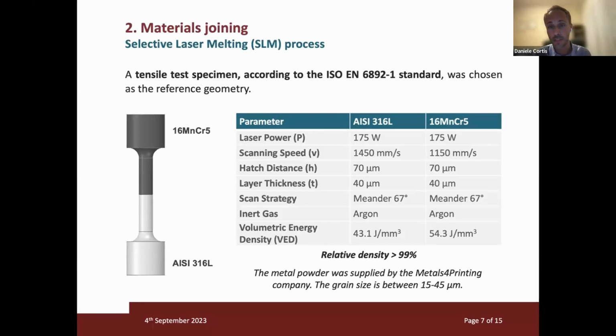Here you can see the process parameters. As you know, the main parameters for this kind of process are the laser power, the scanning speed, the layer thickness, and also the hatch distance, that is very important in our case because we have a very fine laser spot. And of course, you can summarize all these parameters with the volumetric energy density, that is an index for the evaluation of how hard it is to melt the powder. With this parameter setup, we can reach a relative density above 99%. And this relative density has been evaluated before with cubic specimens. For the record, we use powder supplied by the Metals for Printing company with grain size from 15 to 45 microns.